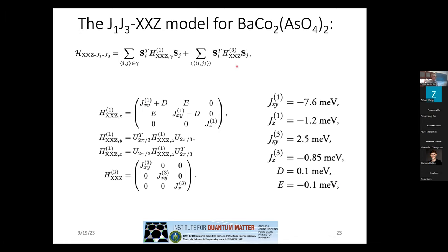But we find that this kind of model that has an easy plane near, next and third near neighbor interaction, and it needs to have these additional off-diagonal anisotropic exchange terms, D and E, appearing in order to induce a gap in the excitation spectrum. Otherwise, it would be an easy plane system and would have to have a gapless mode. So you need these to actually produce the gap at low temperatures.